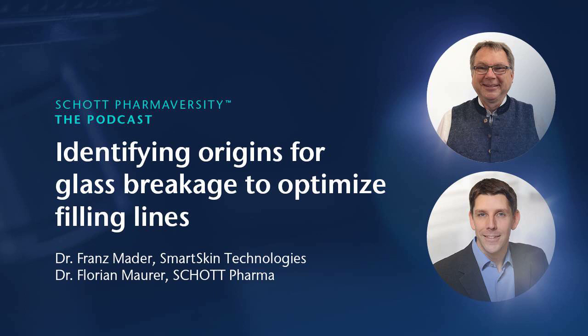Coming back to the comparison to a chain, strength testing is capable of identifying the weakest links. In a subsequent analysis, we examine the broken specimens in more detail by means of fracture analysis or fractography to identify the type of the failure-inducing flaw. This gives a qualitative insight about the nature of the flaw or damage, for instance, what type of contact damage led to failure. We also determine the axial position of the fracture origin, which reveals precious information about where the critical damage was introduced on the container geometry. For example, the heel, the shoulder, the body, the base, or the footprint section.